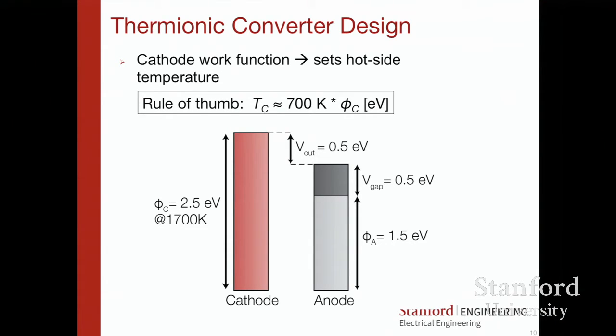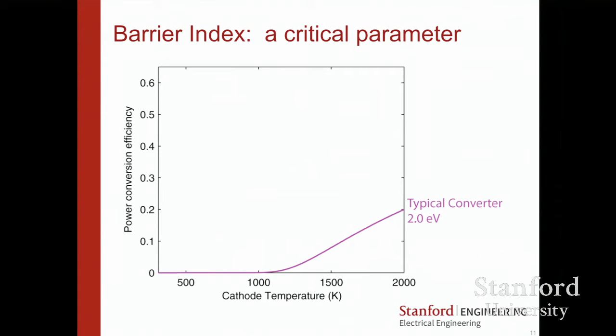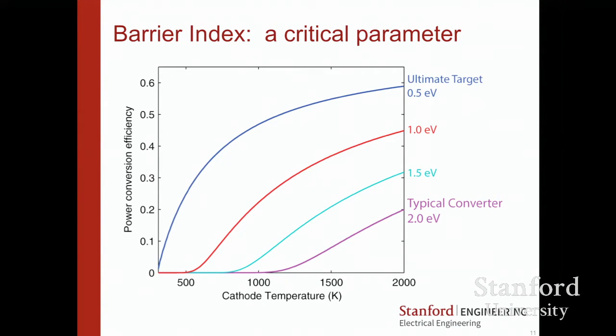So what do they look like if you look at the basic important things? Well, with a typical historical converter, you really don't get a whole lot of efficiency until you get tremendously hot cathodes, because you have a barrier index of around 2 electron volts. Remember, that's the sum of some of the anode work function and some gap voltage. If you begin to work on that, things get kind of interesting in terms of lower temperatures and higher conversion efficiency. And certainly if you get to around 0.5 electron volt, you begin to be able to look at very nice efficiencies that would be very useful in a lot of applications, especially if you have a cold side temperature that's hot enough to run another cycle. So as a topping cycle is where this could be quite useful.